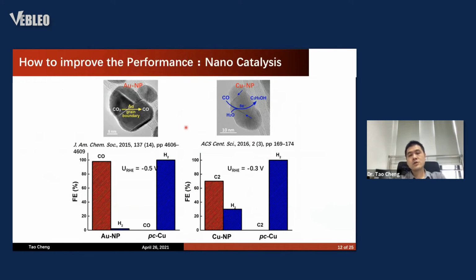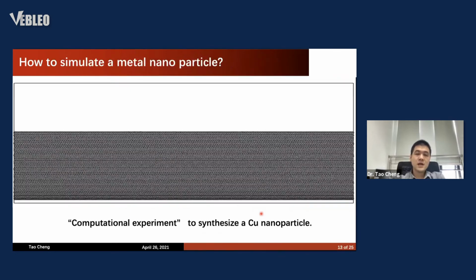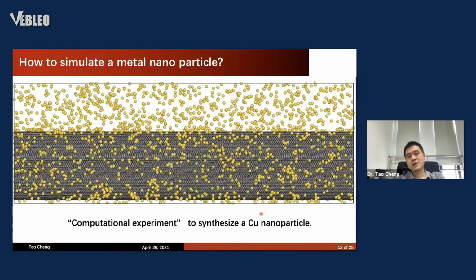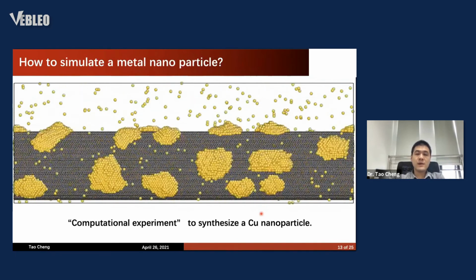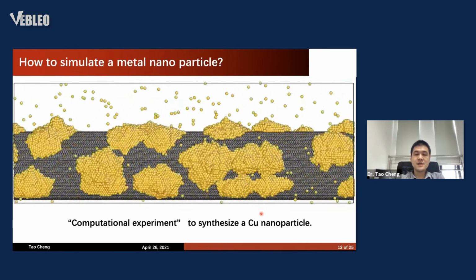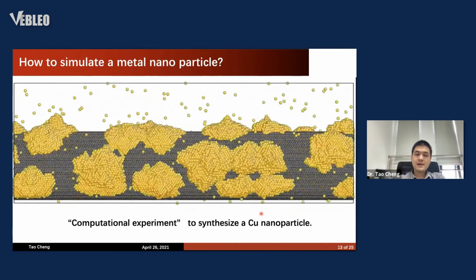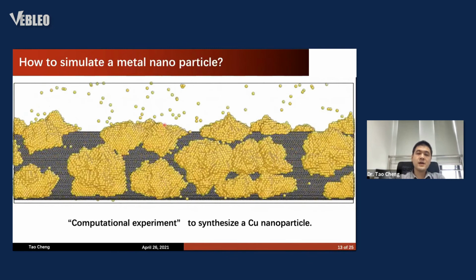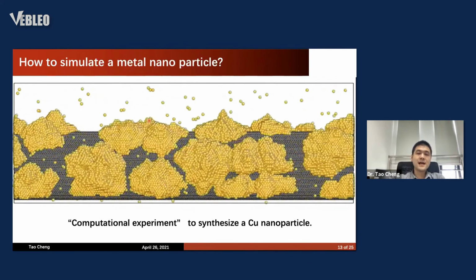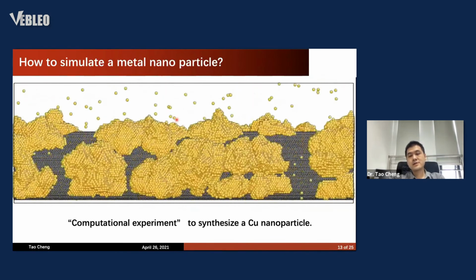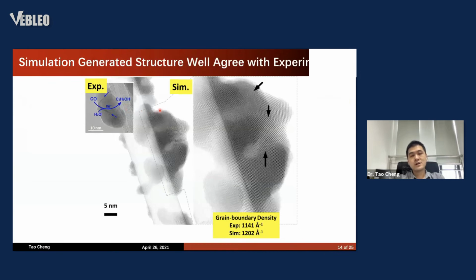So usually, in most cases, the best catalysts are nanoparticles. As we discussed before, the challenge in simulating a nanoparticle is that we don't know the structure. So in our simulation, we developed methods that can computationally synthesize copper nanoparticles. So this is a movie showing how we simulate the growth of the nanoparticle. This is exactly the same as the CVD experiment. Eventually, we end up with a structure like this, which is our simulated structure. And if we zoom in and simulate the TEM images, we can see that this one looks very much like the experimental one.